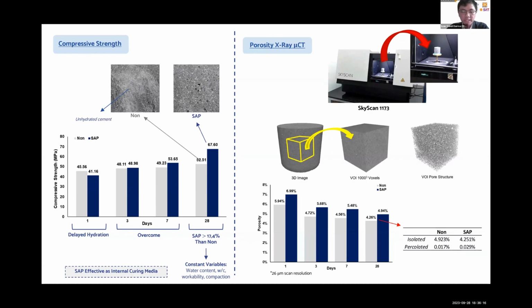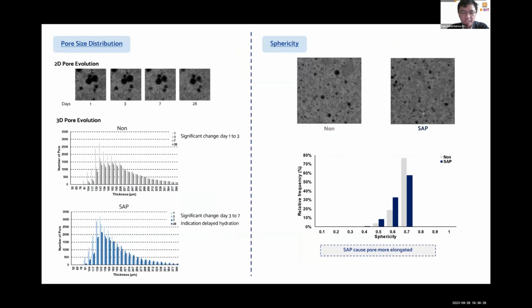Porosity of SAP at 28 days is slightly higher, but the pores are dominantly isolated, so superabsorbent polymer can be assumed to have no significant influence. Through 2-dimension pore evolution, we can tell that pores become isolated through time. From X-ray CT, we can quantify pores in 3 dimensions. In non-SAP specimens, significant change occurs in day 1 to day 3, but